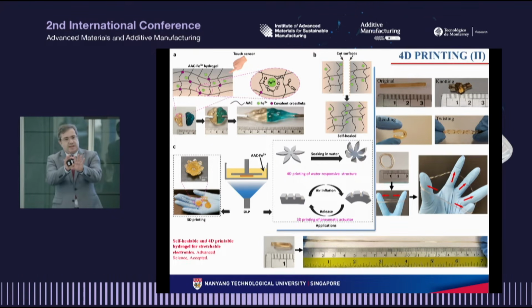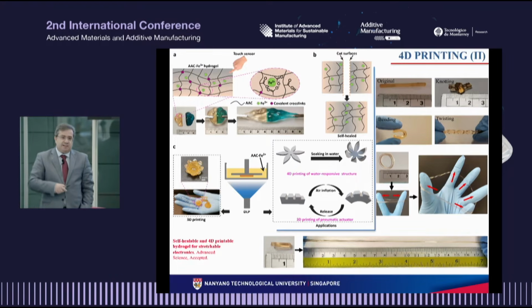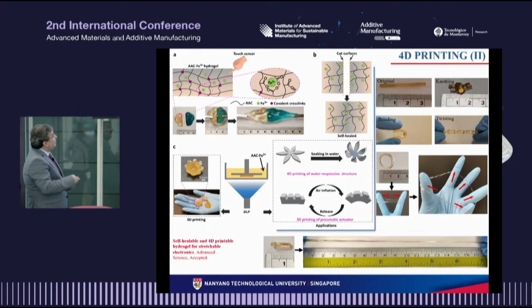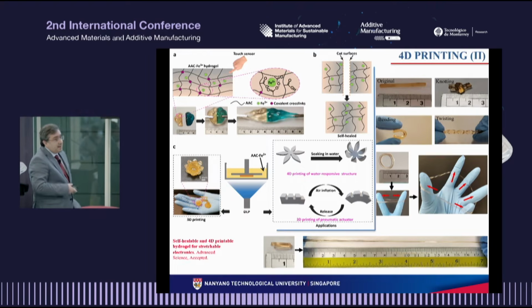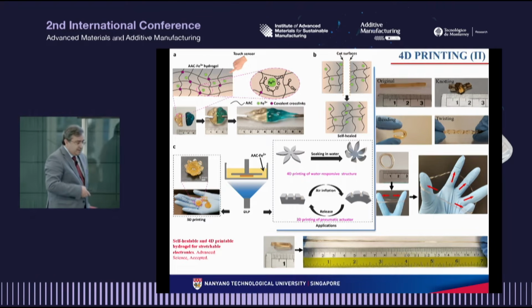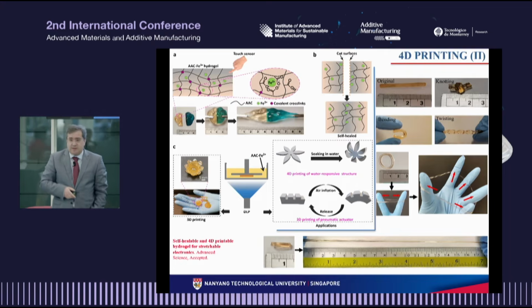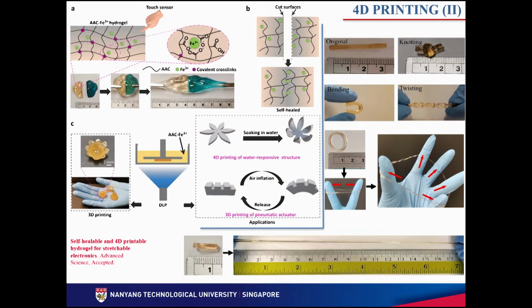two pieces together at room temperature for 1 hour to recreate the original single component. And the recreated single component exhibited again high stretchability. We printed different types of shape morphing materials, soft and pneumatic actuators.